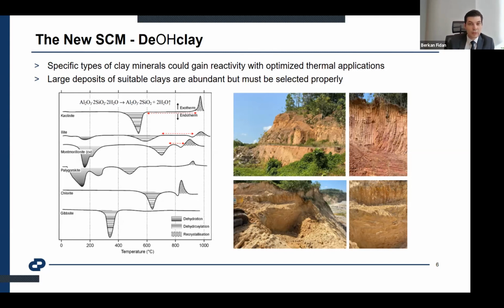These are coarse grains without any hydraulic reactivity, and they decrease the quality and effectiveness of calcined clay as a cementitious material. On that point, the largest range is available in kaolinite, as you can see from here. Illite is just a secondary potential one, but it's a 2-to-1 group clay. Its reactivity is much less than kaolinite, but it could also be effective if it is included in the clay.